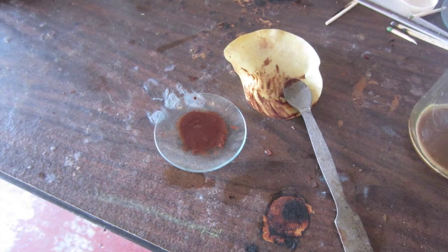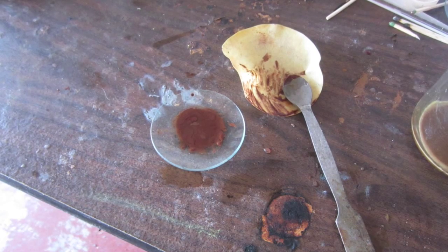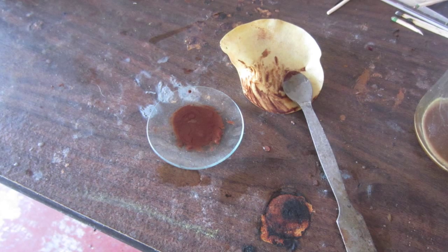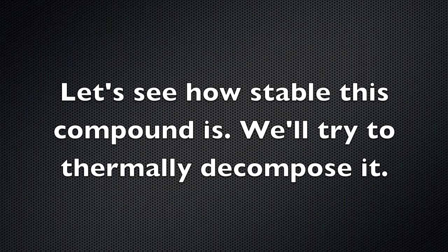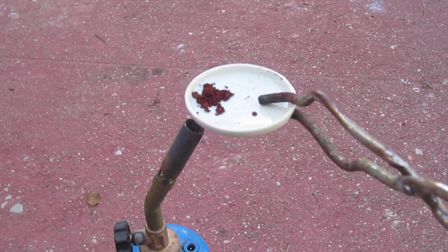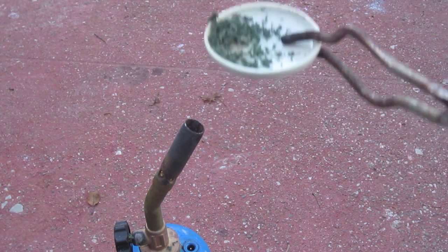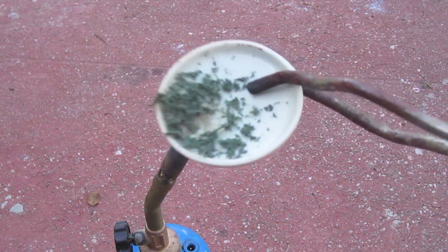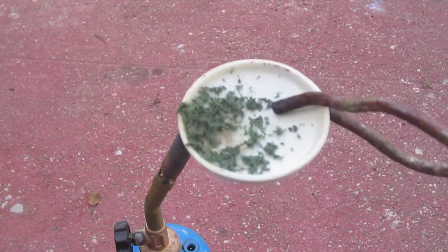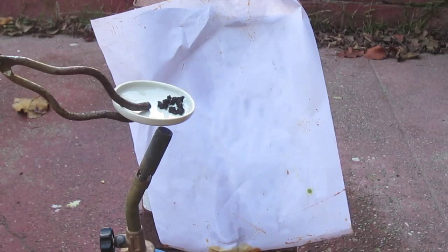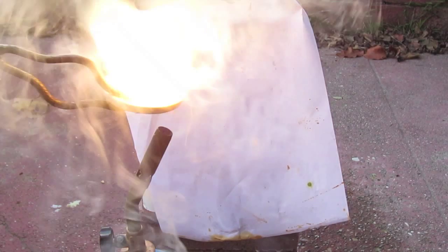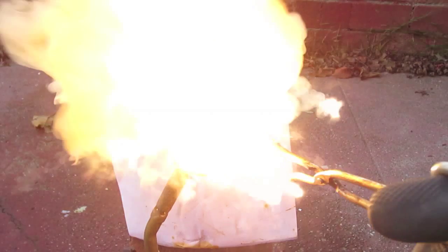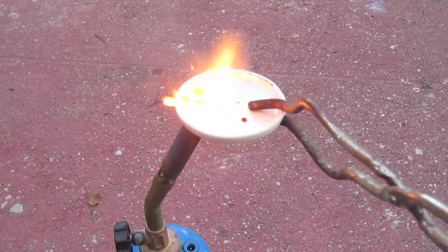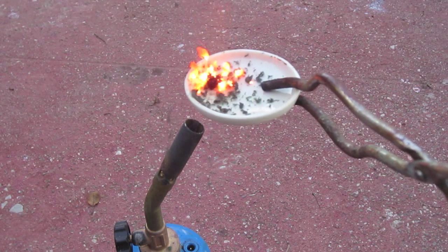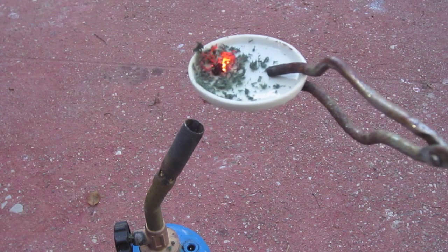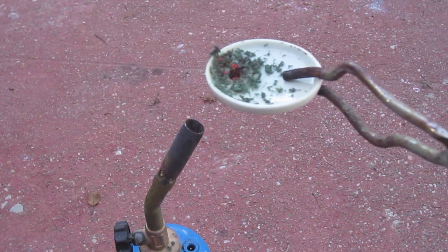What you see there is chromium(IV) triamine diperoxide, a very unstable compound featuring chromium in the rare oxidation state of plus 4. And notice that the resulting compound is a very nice green, which is dichromium trioxide, chromium 3+. So this is very interesting. The chromium 5+ tetraperoxochromate, when it decomposed, went to chromium 6+. But for the chromium 4+ triamine diperoxo complex, it looks like it makes sense energetically for the chromium to go down to the 3+ oxidation state.